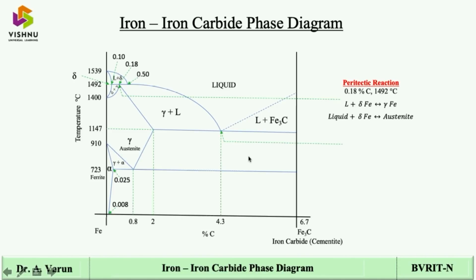The next one will occur somewhere here at 4.3% of carbon and 1147 degrees centigrade. This we call a eutectic reaction. In the eutectic reaction, at 4.3% of carbon and 1147 degrees centigrade, liquid will transform into the ends of the line. You can see very clearly at this end we have gamma iron, which is austenite, and at this end it is Fe3C, which is cementite. So liquid will transform into austenite plus cementite, and this mixture is called ledeburite. That is, austenite plus cementite mixture is called ledeburite.